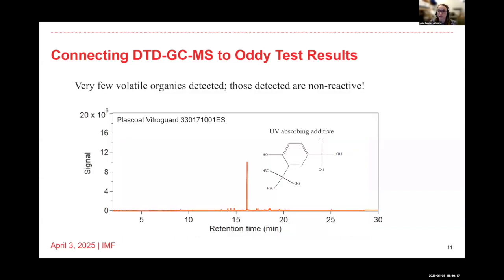Overall, you can tell there are far fewer peaks present in the chromatogram, which tells me that there are fewer volatiles that are being evolved from this material. And of the peaks that we did detect, they didn't represent reactive molecules. And so that's really important. We don't only have to see what volatiles are there, we have to think about whether they are reactive based on our chemical intuition and the literature, and whether they have the potential to damage objects when they come into contact. And so we have the Oddy test that gives us a decent result. And then we can look into the chemical data using GCMS to try and pair those 2 sets of data together.